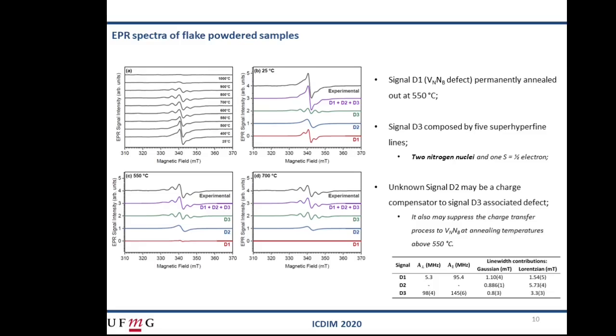Since the VNNB defect was produced by neutron radiation in hBN crystals, we tried to use it to explain the EPR data of powdered samples. However, considering only this defect was insufficient, as can be seen in these figures. Only the signal D1 does not reproduce the experimental data observed from the samples. When the samples were heated at temperatures above 500 degrees, a structure composed of 5 lines is clearly observed in the spectra. So the model considering the signals D1 and D2 used for crystalline samples needed to be improved with a third signal called D3, to be able to generate the observed 5 lines.